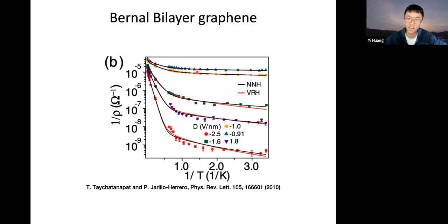So he instead looks at the lower temperature regime where the slope becomes smaller, but they have more points. So they find that the activation energy related to this slope is also more than 100 times smaller than theory predicts.